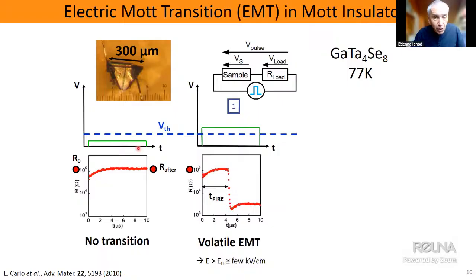But what we have observed, which was a big surprise at that time, is that if we exceed a threshold value, a threshold voltage or threshold electric field, then look at what happens in the middle of the pulse. Here, after 4-5 microseconds, we have a sudden drop of the resistance by almost 2 orders of magnitude. And what is interesting is that when I stop applying the electric pulse, this resistance relaxes. We call that a volatile electric Mott transition.